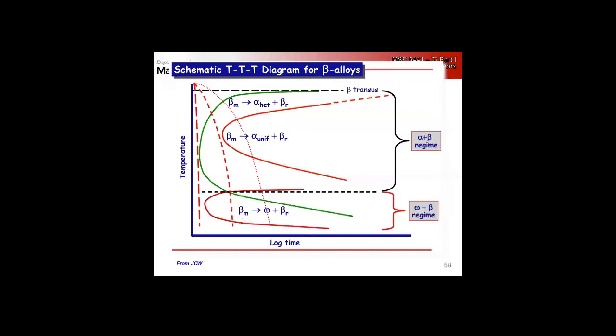Well, so this is almost like straight down. Basically, you miss both of these, and you'll end up, depending on the alloy, if you have enough beta stabilizers, you'll just remain as pure beta. If you're at the lower end in the near beta alloys, you'll end up with martensite, a fine dispersion of alpha prime or alpha double prime. So what you're going to get is going to be very strongly dependent on where in that near beta to beta range you fall.